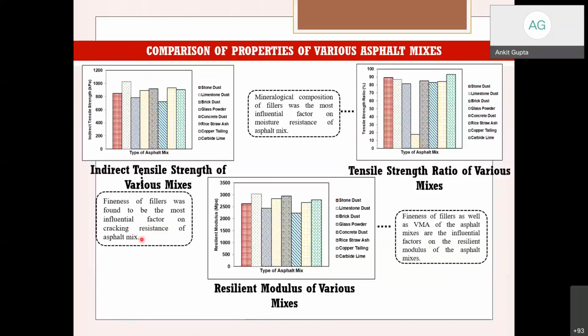for the cracking resistance of the asphalt mix. For the resilient modulus, again the fineness of the fillers as well as the voids in the mineral aggregates are the influential factors. And for the tensile strength ratio, that is the moisture sensitivity test, if you leave out the glass powder, all are showing satisfactory results. It is only the mineralogical composition of the fillers that is the most influential factor for moisture resistance, because there is a high silica content. That's why the tensile strength ratio for the glass powder is low.